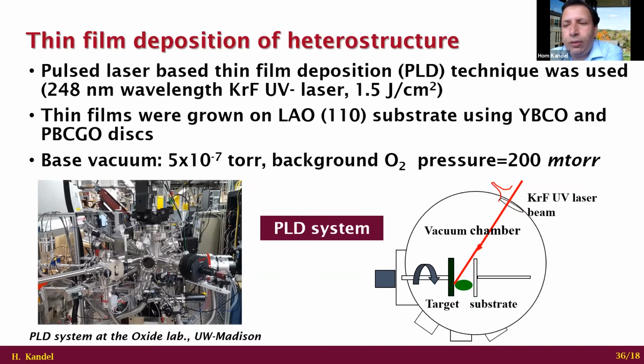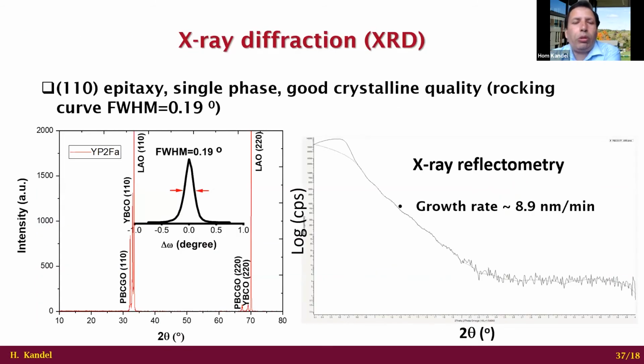Next slide, please. So we perform different types of testing on the heterostructures. For example, X-ray diffraction is one of them. The reason we perform X-ray diffraction is to check the 110 epitaxy, that is, also to check the pure crystalline state of the film. We also perform XRR to determine the growth rate of the heterostructure.